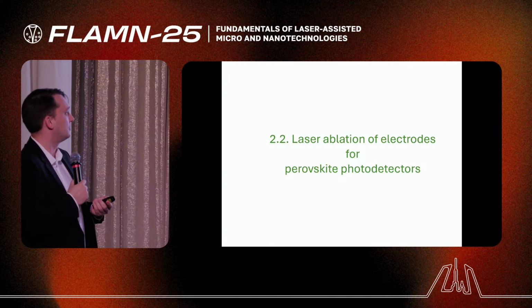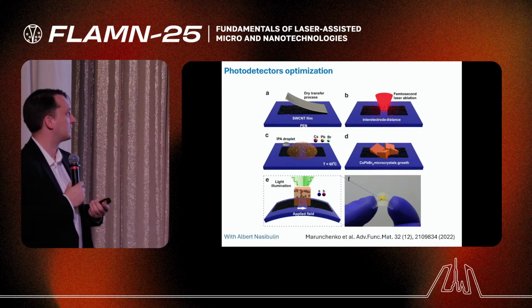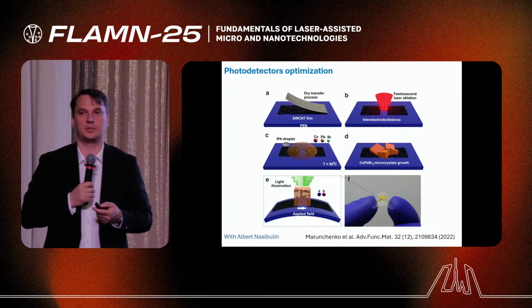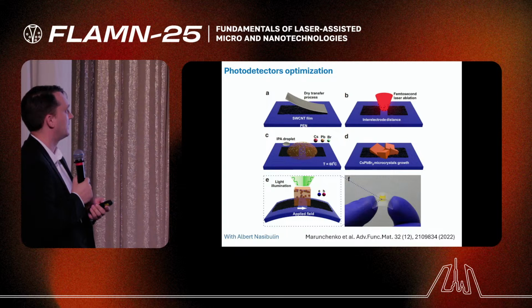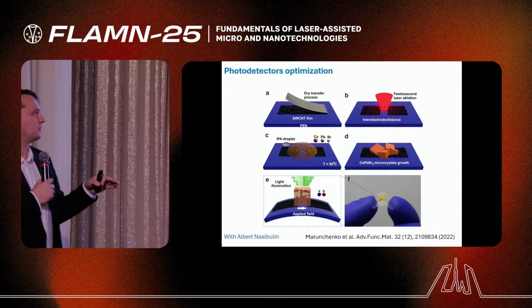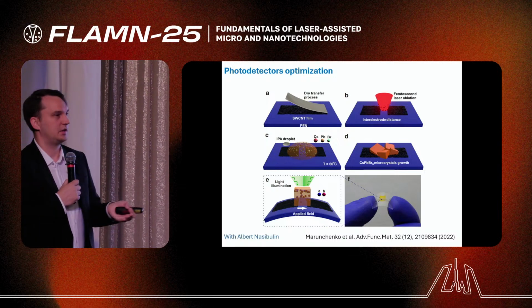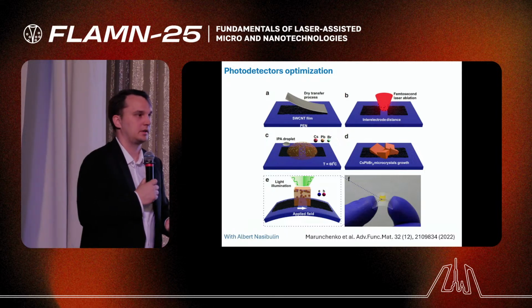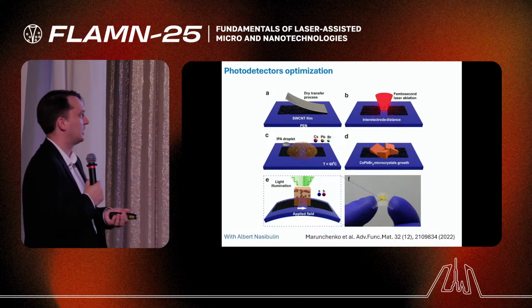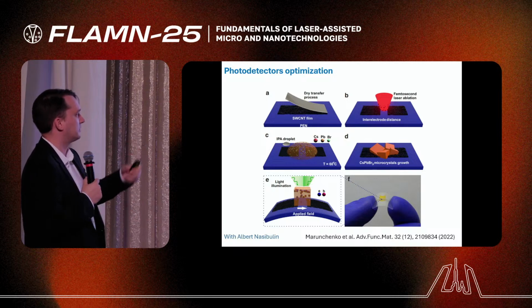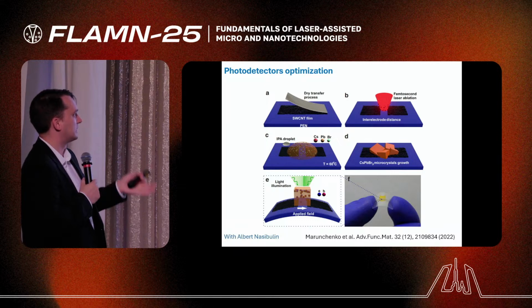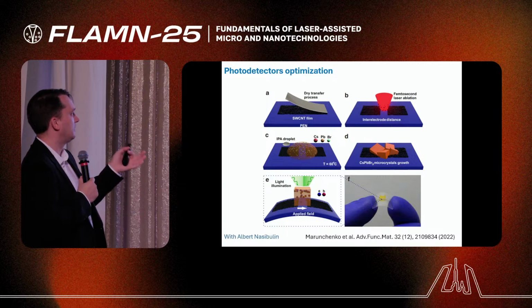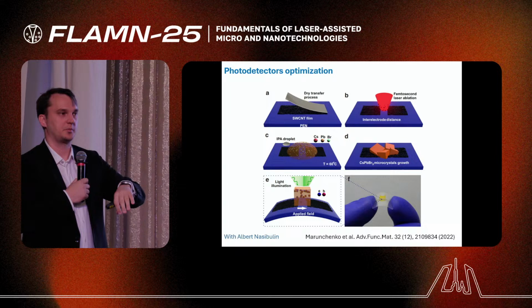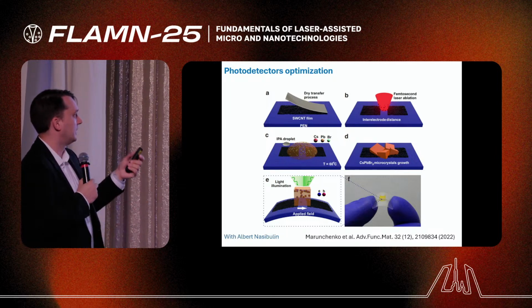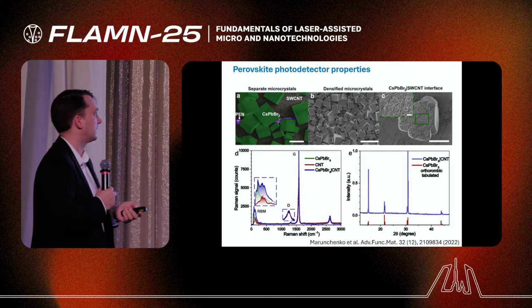And let's go further to photodetectors. How can we apply laser ablation for photodetectors? Here are our collaborative works with Professor Albert Nasibulin from Skoltech, and his nice carbon nanotubes. They are in the form of sheets which can be cut by laser very carefully, especially if we work with a flexible substrate, where we should cut it without damaging or changing too much the substrate properties and smoothness. After cutting precisely with a femtosecond laser this single-wall carbon nanotube film, we deposited the solution with precursors, and then we grew perovskite single crystals. In principle we can apply voltage to such a system, and we will have photodetectors.